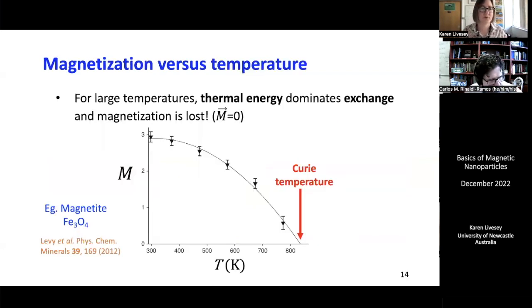Here is a plot I took from an article, mainly because it is of magnetite, which is often our material of choice. And this is the magnetization in some units I don't want to tell you about. And here is the temperature on the x-axis. And so you can see I start out with quite a high magnetization. Then as I heat it up to, say, 820 odd Kelvin, the magnetization goes down. And then after this point, the magnetization has vanished. And this critical temperature where the magnetization vanishes is known as the Curie temperature.